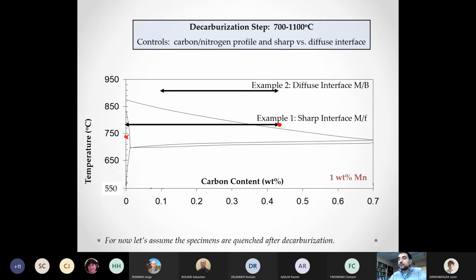If we decarburize at a higher temperature, the same steel, but at a higher temperature, let's say at 950 degrees or 925 degrees, there is no ferrite at the surface. It will be a continuous gradient within austenite. And of course, we don't have to keep the surface concentration as zero. That's also a parameter we can control. We can make the surface concentration anything we want by controlling the carbon monoxide to carbon dioxide ratio in the gas. So we have control over the surface concentration, and we also have control over whether or not there is an interface, and we have control over the depth of the decarburized region by controlling the temperature and the time we use.